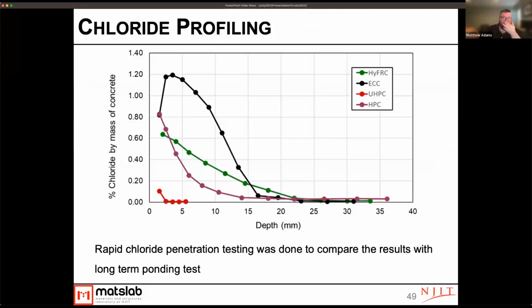We also did some chloride profile measurements. And again, what this is showing us is the depth of the concrete along the x-axis and the amount of chloride by mass of concrete along the y-axis. As you go deeper, you tend to get less chloride in that system because it takes longer for those chlorides to get down there. So this was done at a year of ponding in that G109 test.